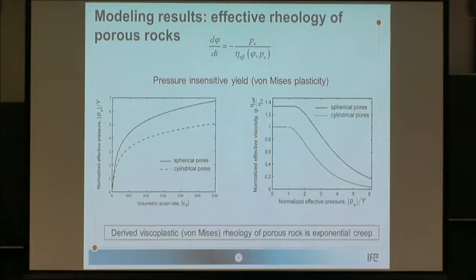So what we get from averaging procedures, and here I will stop on the case of viscosity and viscoplasticity. Elastoplasticity will be pretty similar. So there is a certain correspondence between viscous and elastic cases. In the case when viscous deformation and plastic flow act in parallel, the difference that it adds to our porosity equation, to our compaction equation, is the dependence of effective bulk modulus on effective pressure. So our bulk modulus is not only a function of porosity, which we saw on the previous slide with all these curves of effective viscosity, but also of the pressure.